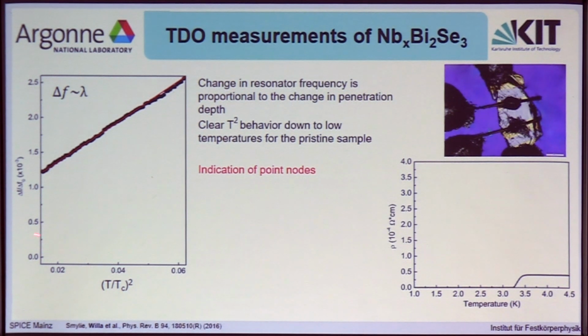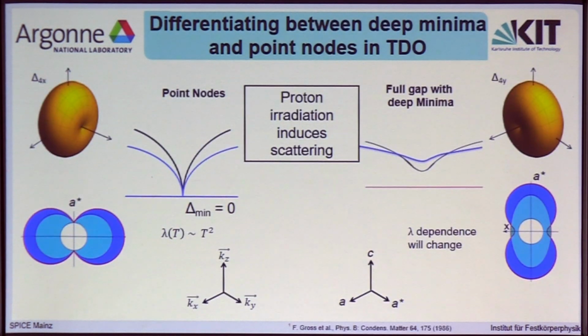However, even though we are measuring to quite low temperatures compared to the superconducting transition temperature, you could still argue that since the minimum is expected to be very low, we are not reaching low enough and we are fooled by this T-squared dependence. In order to exclude that, we conducted proton irradiation of our samples. So what does proton irradiation do?